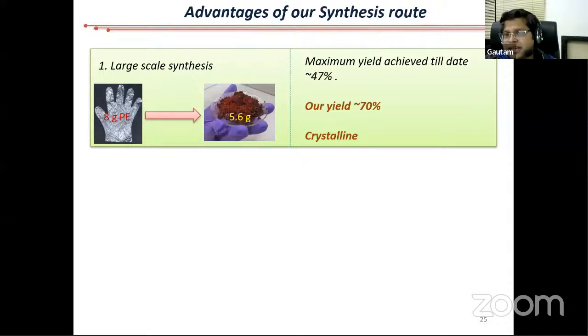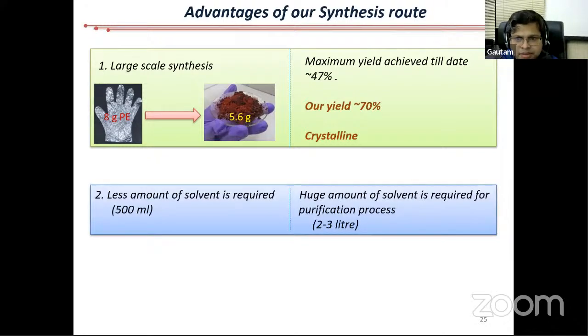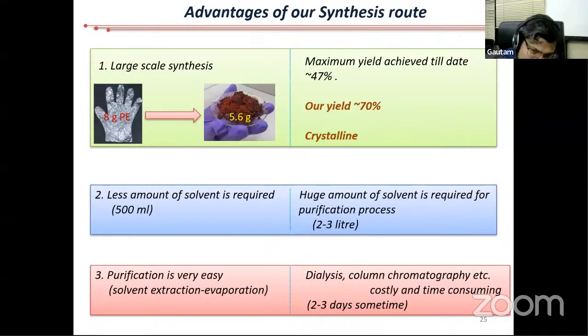And then it is crystalline. I showed you the graphene sheets. You can see those graphene layers. So this is crystalline. Normally, you will find carbon dots which are amorphous. Only 5 to 10% of the known carbon dots are actually crystalline. Others are amorphous. So then I will not get into more specifics why this synthesis is very good compared to what is known,